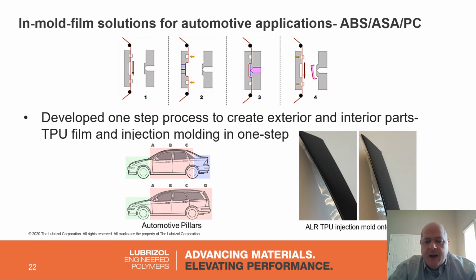And you can see that in some of our pillars or black plastic simulating pillars on the bottom right there, where you can actually see that the ALR TPU is basically over the ABS plastic. In this particular case, the TPU is going to give UV resistance, scratch resistance, but it also glosses up the ABS film to 80 to 90 gloss range. Again, this can be replacing a paint process or a hard coating process, or perhaps even a dual shot application to where you're putting something over the ABS to protect it.